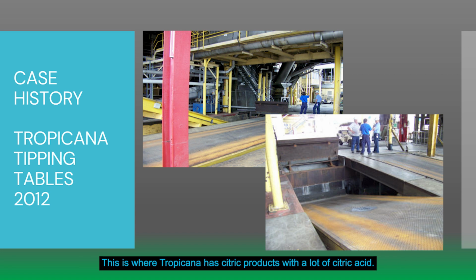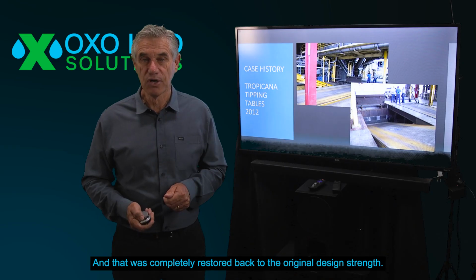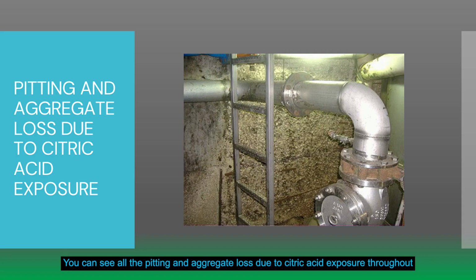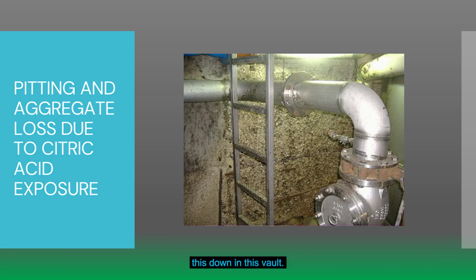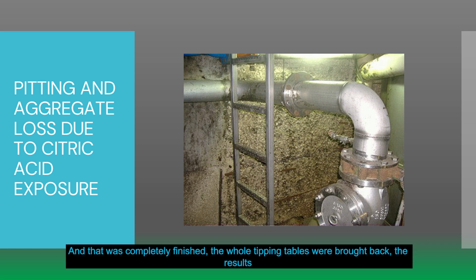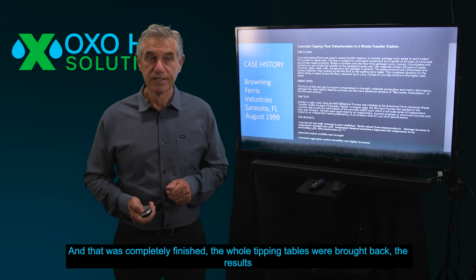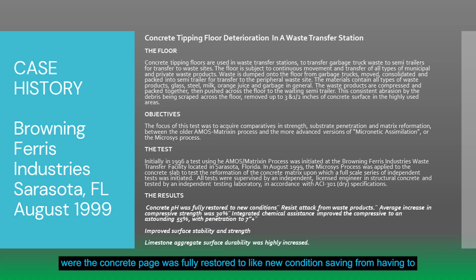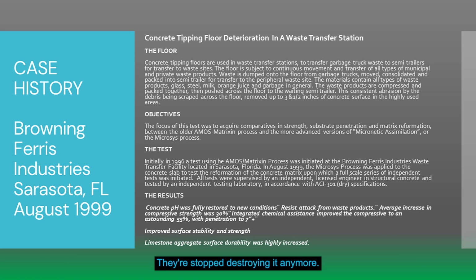Tropicana tipping tables. This is where Tropicana has citric products with a lot of citric acid, and there was a lot of degradation in the concrete throughout that, and that was completely restored back to the original design strength. You can see all the pitting and aggregate loss due to citric acid exposure down in this vault, complete deterioration, and that was completely finished. The whole tipping tables were brought back. The results were that the concrete pH was fully restored to like-new condition, saving from having to tear it all out and replace it. It resists attack from the citric acids in the fluids there, which stopped destroying it, and it's basically an overall success.